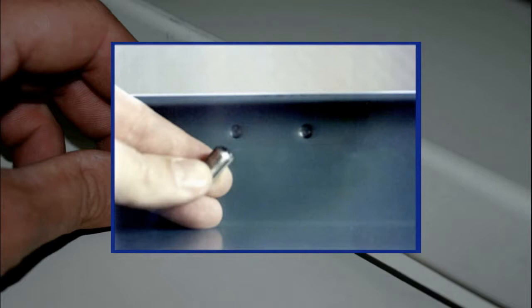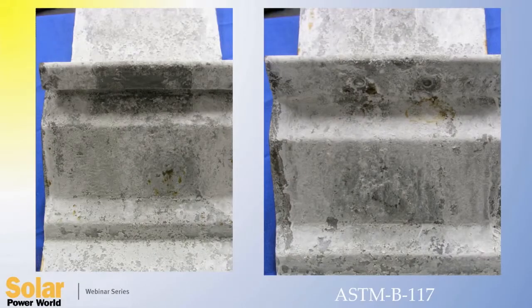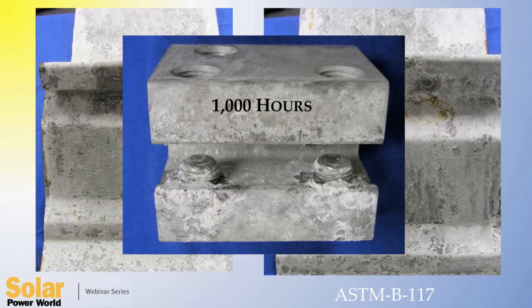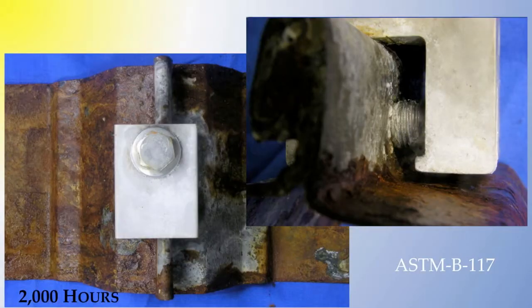S5 has also done extensive salt fog testing of the attachment to prove no premature corrosion to the roof. While 1,000-hour testing is considered the industry standard, we have doubled that, testing for up to 2,000 hours. And as you can see, even after the Galvalume coating has completely corroded from the salt fog chamber, the clamp and set screws have not caused any corrosion to the roof material.